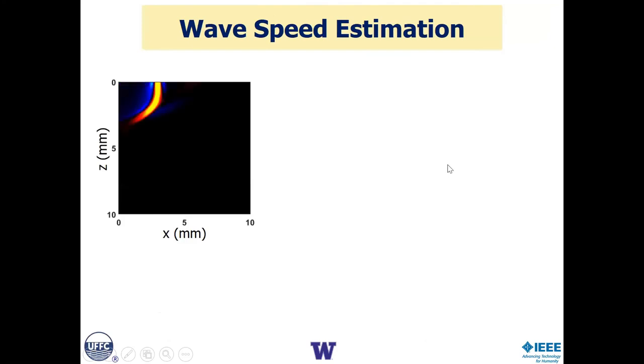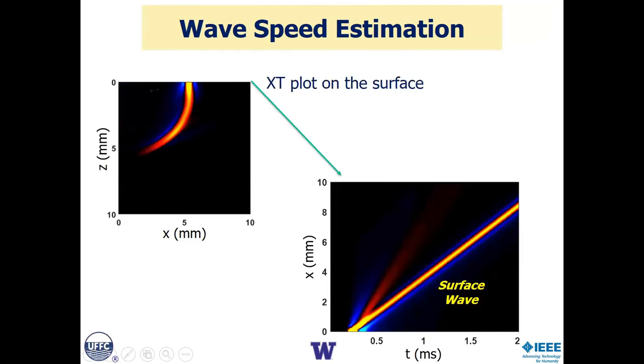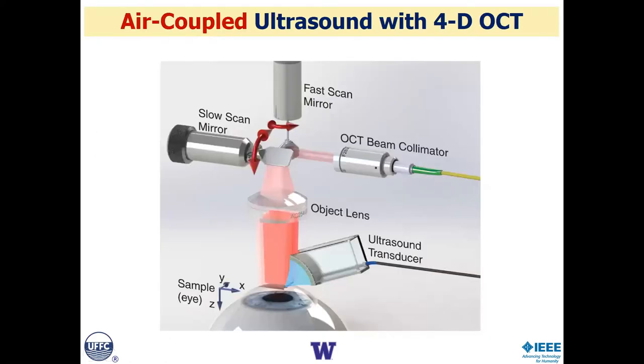So how do we make wave speed images? Well, we can look at wave propagation. If I just look along the surface and make an XT plot, this is the position along the surface, this is time, we can see that surface wave propagating. And so if we take local derivatives, we can get local estimates of the wave speed. So that's what we did. We put a system together, which has the real-time 4D OCT system integrated with our air-coupled transducer.